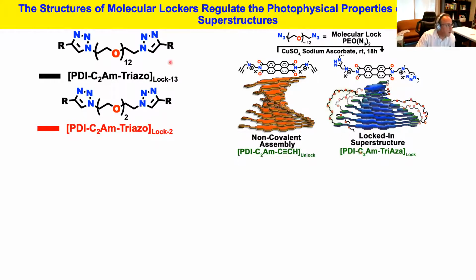The data I showed you so far was with what we are calling the longer locker in our lab. It's a lock 13, so it's around 12 to 13 ethylene oxide repeating units. And what we have done is the same type of chemistry, but using a shorter locker that is only composed of 2 ethylene oxide repeating units. We are using exactly the same type of chemistry to do that.